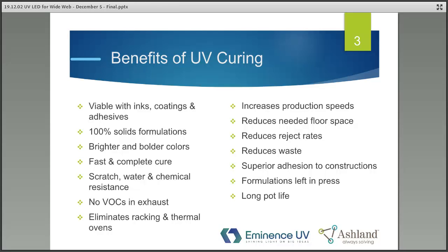The particles that are used in the formulation are very tiny, and so they behave like a liquid even though they're effectively 100% solid. What that means is you're not flashing off anything. When it's cured or cross-linked, that process happens very fast, and you get a very complete cure, an instant cure. For inks, it'll give you brighter and bolder colors. For coatings, top coats, you'll get scratch, water, and chemical resistance. There's no VOCs that have to be exhausted out of the building or burnt in an afterburner. So a lot of this is very advantageous to the installation, as well as the benefits that you'll get on your printed product.